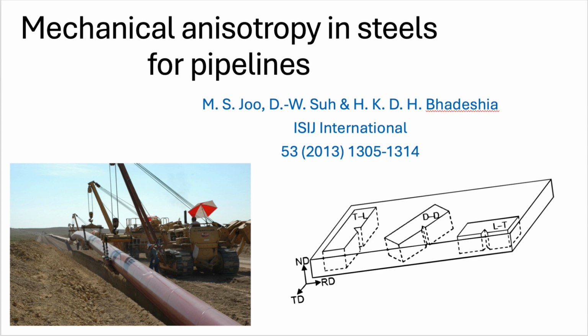Culprit number one, unwanted guests, the non-metallic inclusions. Right. These are basically tiny impurities left over from steelmaking, things like manganese sulphides, silicates, aluminum particles. They're always there to some extent. But the problem isn't just that they exist, it's what happens when you roll the steel plate hot. Exactly. The hot rolling process involves massive plastic deformation. This squashes and stretches everything, including these inclusions. They tend to get elongated and line up along the rolling direction. Like tiny weak threads running through the metal?